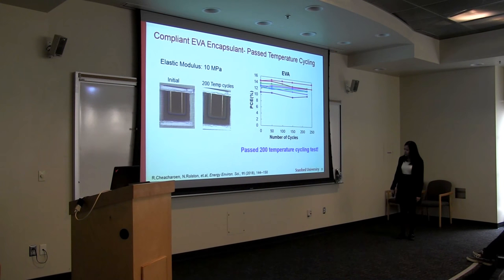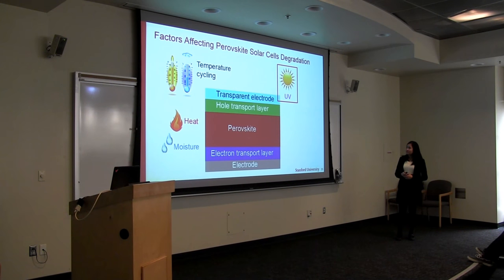So in this study, we learned that in selecting a suitable encapsulant, we need something that's flexible, meaning something that has a low elastic modulus to withstand the temperature cycle. Now, let's look at the second factor. What happened when we shine a UV light on the perovskite?